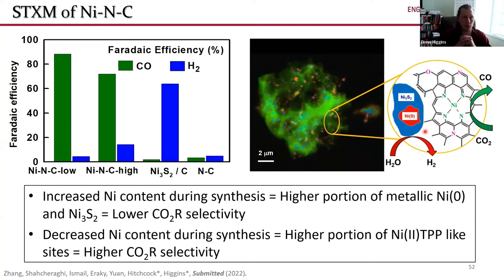And those ones that were exposed were actually more selective towards producing hydrogen. So the more of those we had in there, the less selective our catalyst was towards carbon monoxide. So this was just a nice way to get this spatial distribution, so to get this insight into the types of active site structures present in these catalysts and figuring out exactly where they are present.